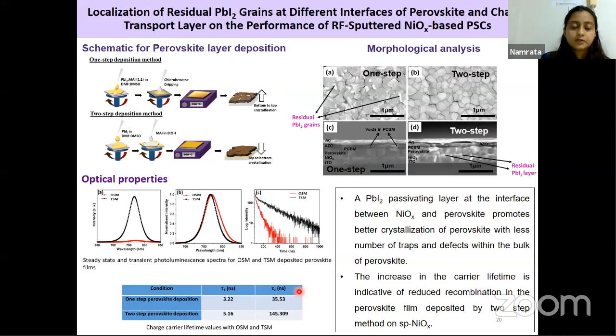So we compared the deposition techniques and the results from these deposition techniques. So briefly, let me explain the difference once again. In the schematic for the perovskite layer deposition, the first is the one-step deposition method, where we can see we have one solution and the perovskite is formed immediately after annealing the spin-coated perovskite solution. Whereas in the two-step deposition, we first deposit PbI2, we spin coat it, and then we add MAI, anneal it, and then we have a perovskite. So we have a PbI2 layer at the bottom and a perovskite layer on top.